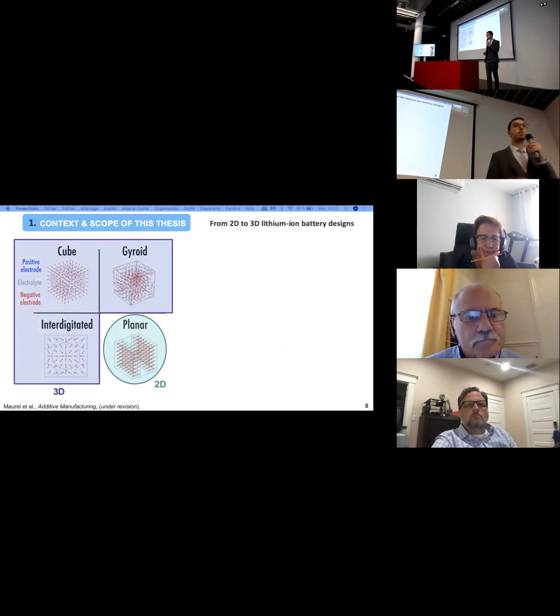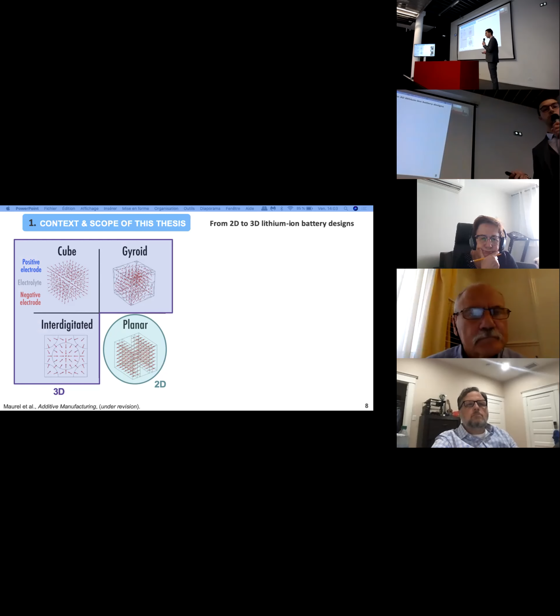you can see the lithium-ion diffusion path, and you can see that in planar two-dimensional electrodes, a two-dimensional battery system, the lithium ions are just moving in one dimension between the electrodes, so simply doing the shuttle. While in three-dimensional architectures of the battery, such as the gyroid here, you can clearly see that the lithium ions will move through the whole space in three dimensions.